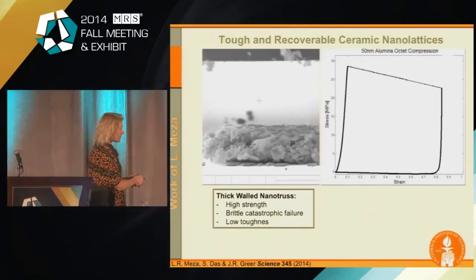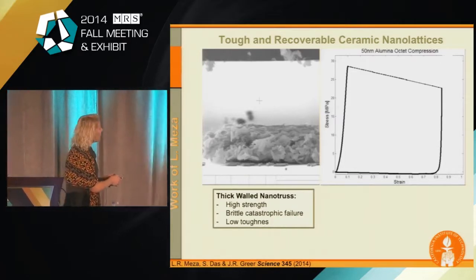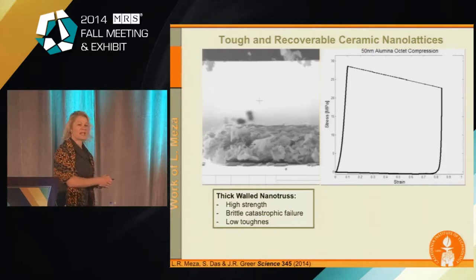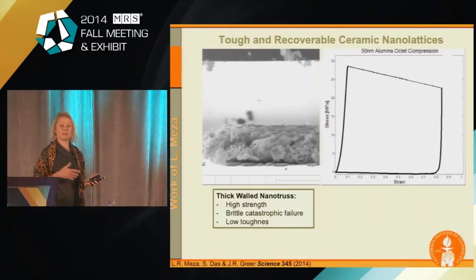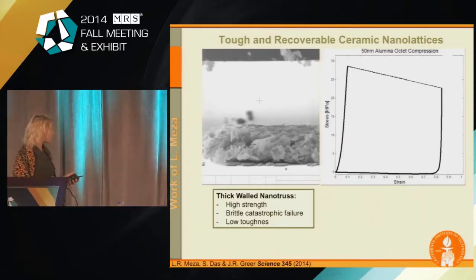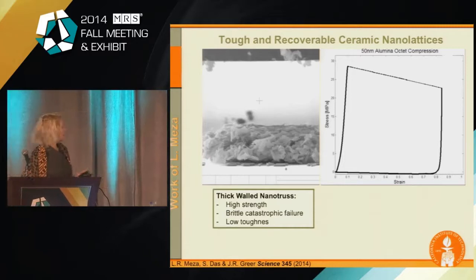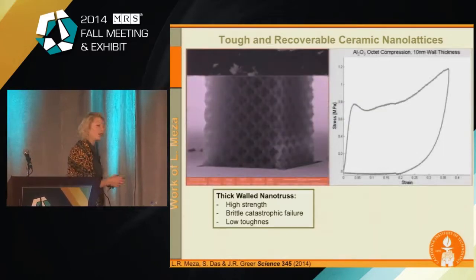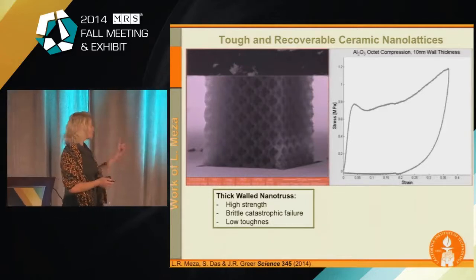For something that's this much air, that's 99% air, it's about 27 MPa. So the fact that we're able to measure the strength still in MPa actually means something. So they remain relatively strong, even being this thin-walled. Now, we're an experimental group mainly, so we don't give up at just a single experiment. So here's what we're going to do.